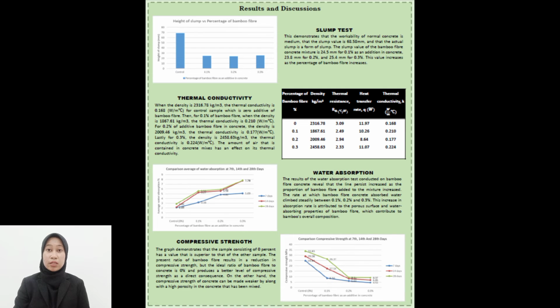Next is water absorption. The result of the water absorption test conducted on bamboo fiber concrete revealed that the water absorption increased as the proportion of bamboo fiber added to the mixture increased. The rate at which bamboo fiber concrete absorbed water climbed steadily between 0.1%, 0.2% and 0.3%. This increase in absorption rate is attributed to the porous surface and water-absorbing properties of bamboo fiber, which contribute to bamboo's overall composition.